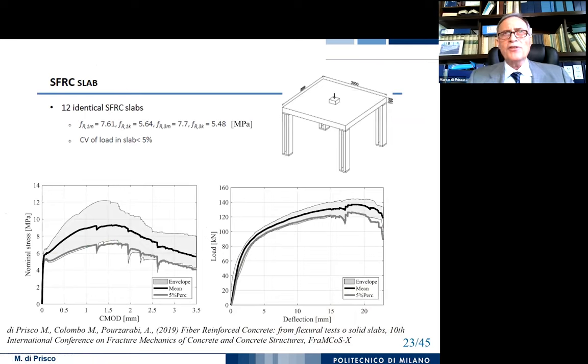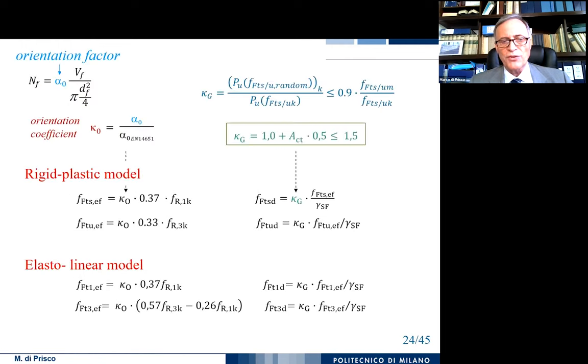Well, another concept which is very important for fiber-reinforced concrete is that usually we have also a difference between the behavior in the beam and the behavior in the plate. And you see that the behavior in the beam shows a much larger scatter than what we can have in a real structure. That means that when you have in a structure the possibility to have different resistant mechanisms working in parallel, you reduce the global scatter of the response.